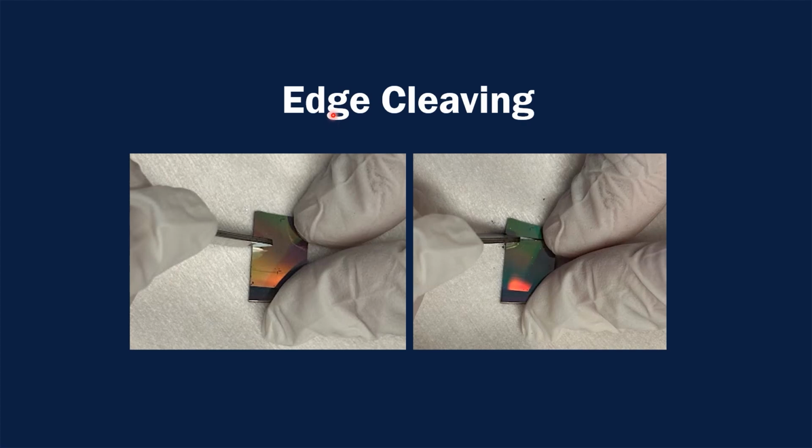Cross-sectional SEM view is often needed for applications like coating thickness measurement, process verification, and failure analysis. So what is edge cleaving first? This is a simple way I make the sample by pressing hard on the edge of a sample using the back end of a tweezer till the sample cleaves along the direction pressing down. Then you can mount the sample vertically for SEM imaging.